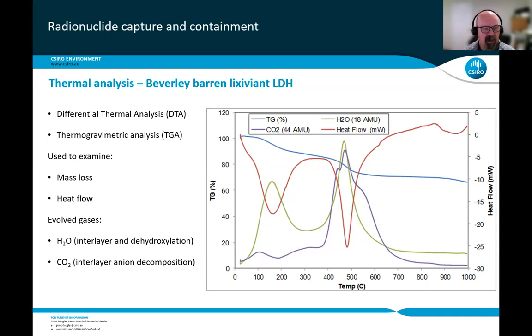So if you look at the first line there, the TG, which is the mass in percent, that's the blue line. So we obviously start off at 100% there. And as we heat it up to 1,000 degrees, we end up going down to about 65%. So just simply heating the layered double hydroxide, you can lose about 1/3 of the mass. So that's just a really neat way if you want to reduce the final mass of the LDH, even though it's really, really small to start with, you can still reduce it by about 1/3 just by heating it up. And you probably don't have to go above about 700 degrees to do that.